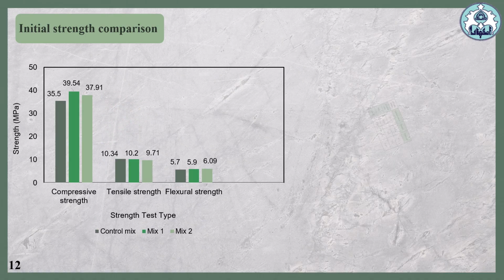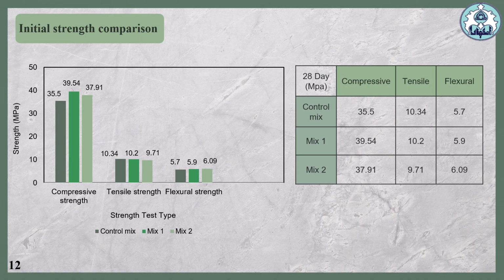These results present the 28-day mechanical test outcomes for the 3 concrete mixes. In terms of compressive strength, Mix 1 containing 100% slag cement showed better performance compared to Mix 2 and the control mix. For tensile strength, although the slag-based mix exhibited slightly lower values than the control sample, all results remain within the acceptable range of C30 concrete, which was the target strength class of this study.